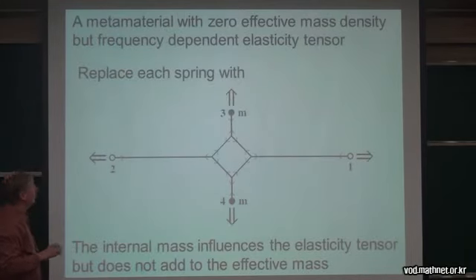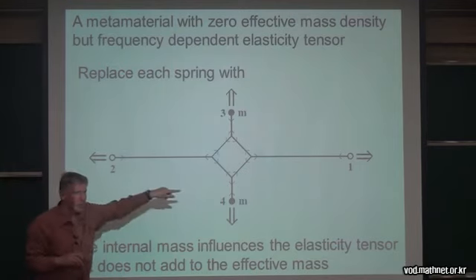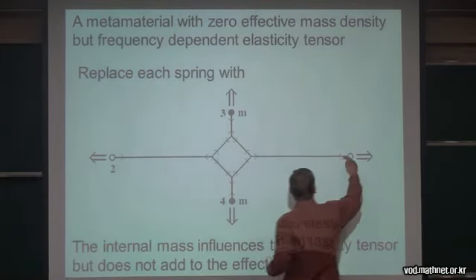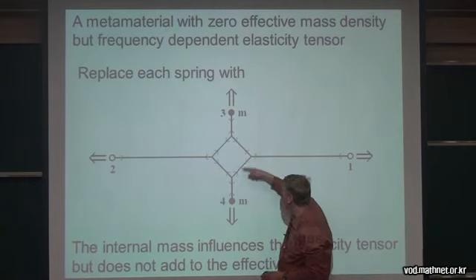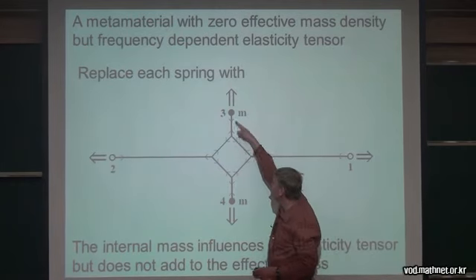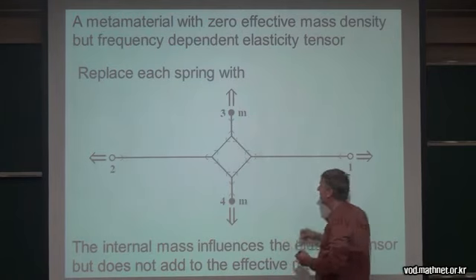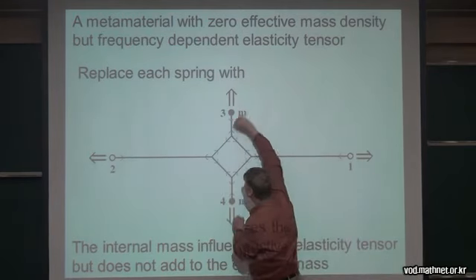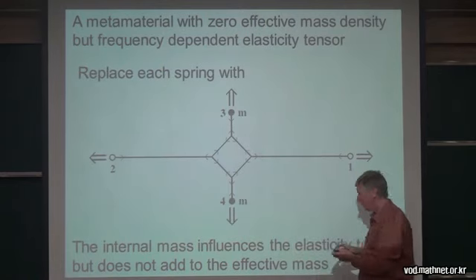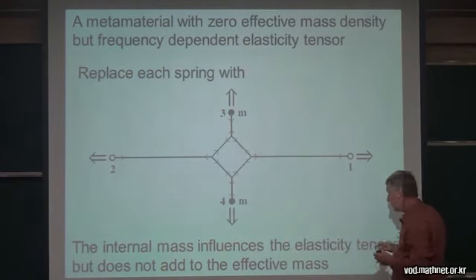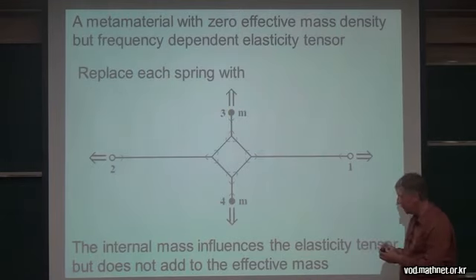And you can actually get metamaterials with zero effective mass density but a frequency-dependent elasticity tensor, and the idea is to replace each spring with this type of geometry here. So there's springs here, and we've got some square of springs here and masses attached to this end here, and so if I pull this in this direction here, this will excite these masses there, and so the internal mass influences the elasticity tensor, the stretch, but does not add to the effective mass,